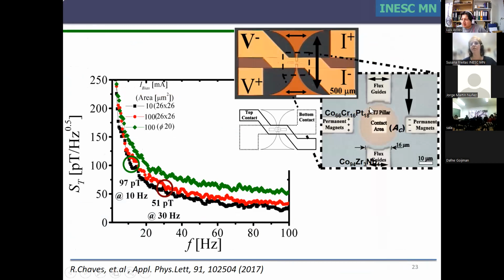Here the idea is to have a round shape around the tunnel junction, so the TMR sensor was round. The reason for being round is to not have an anisotropy, so as to minimize the magnetic domains trapped in the corners. Then the flux guides follow this circuit. I see here that this is very irregular, not a smooth angle. This is because of the lithography limitations when this was done, and also it was simulated to have these small edges here, to trap the magnetic domains of the flux guide itself, so that it has a smooth performance along the full range of the linear field.